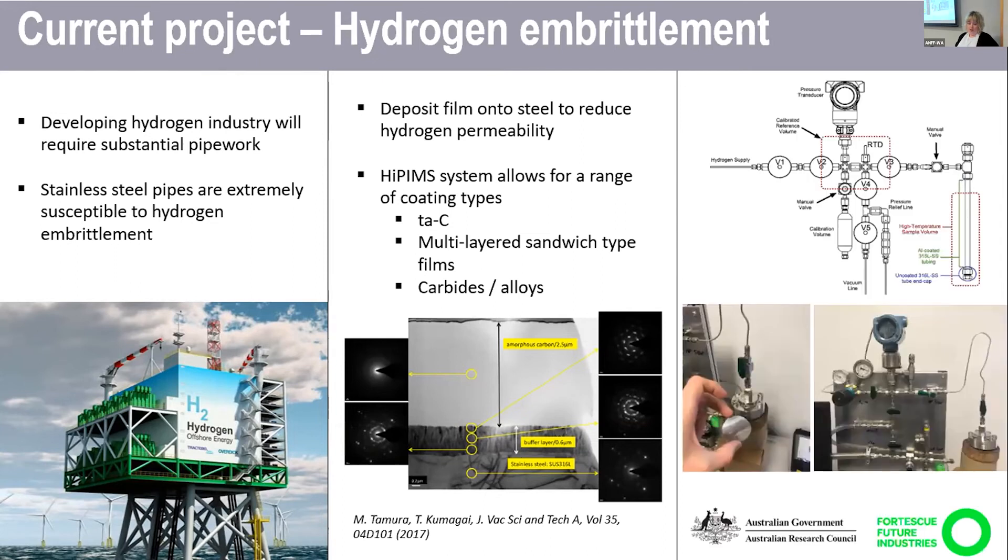We currently are working with another group at Curtin using this hydrogen testing system. So one side is under vacuum, one side is under hydrogen pressure, and we will deposit films onto these stainless steel tablets and test how much the hydrogen can get through.